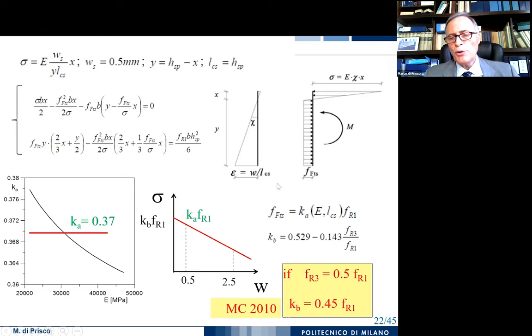And then you can also evaluate the KB, which corresponds to the value when the stress is not equal to 0.5, but is equal to zero. And you can obtain this type of relationship. In the Model Code, we did even a further simplification. So we imagined to be in the smallest class, so class A. So the relationship between FR3 and FR1 is 0.5, as you can see here. And at the end, you can obtain the KB value, so the value for the crack mouth opening displacement equal to zero, equal to 0.45.